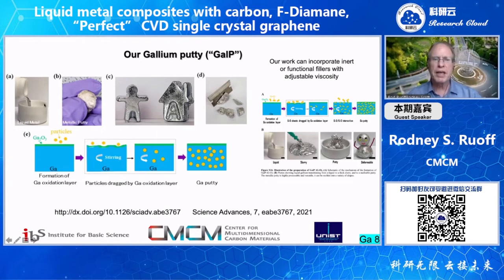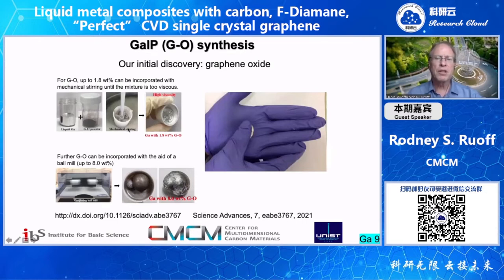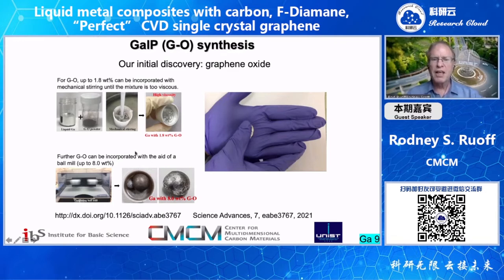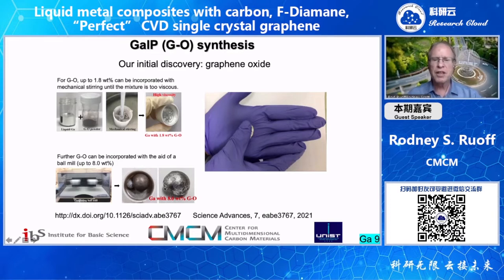The question arose: why did the graphene oxide seem like it was wetting? That spurred me to ask Chun Hui to try to make a new type of composite with a liquid metal. At first he mixed by hand in a mortar and pestle, but eventually we used mechanical devices — a stirrer and ball milling. We learned that as long as we were doing the mixing in air, we could form these putty-like composites in which the viscosity changed with higher filler concentrations. Using ball milling, we could get about eight weight percent graphene oxide.